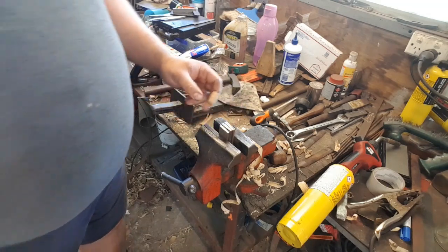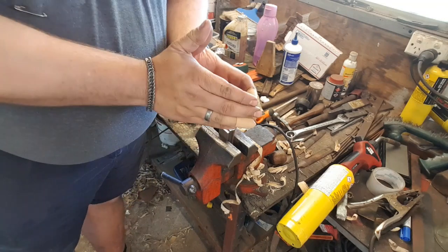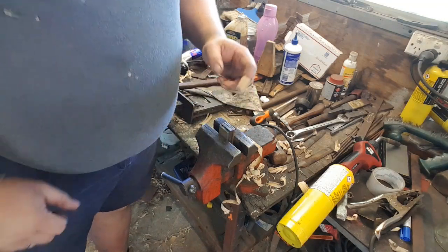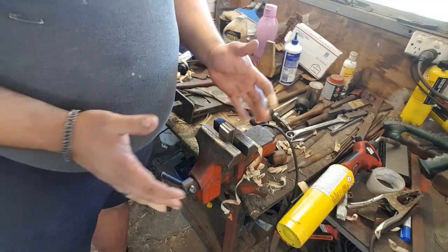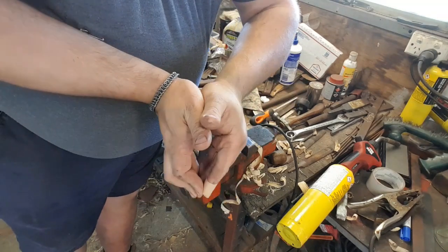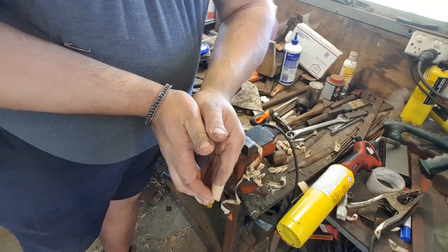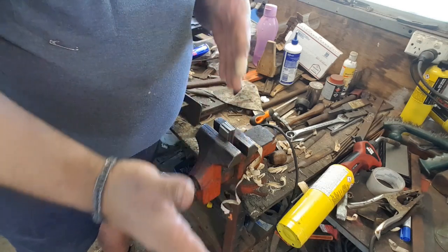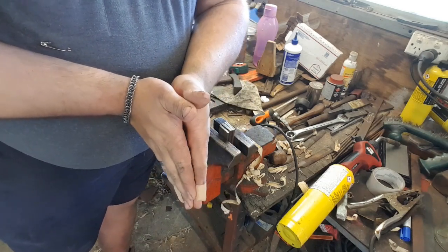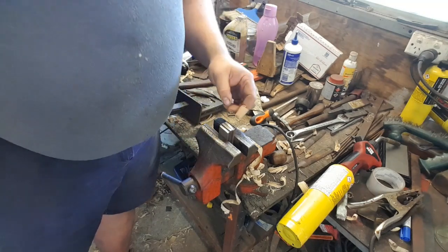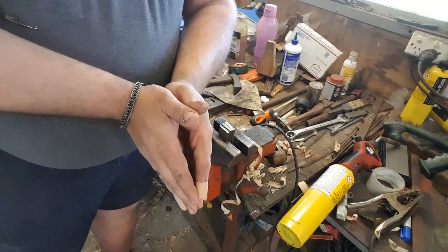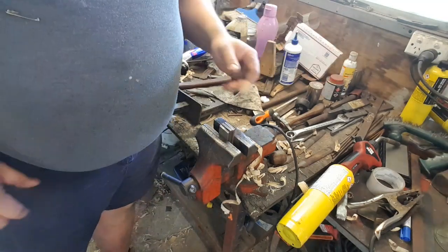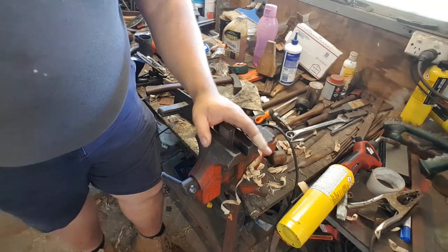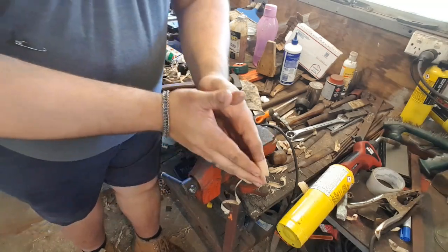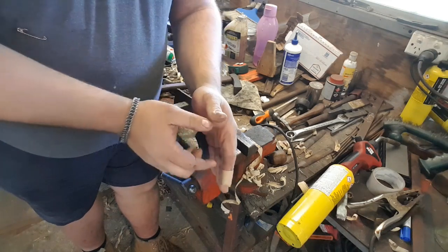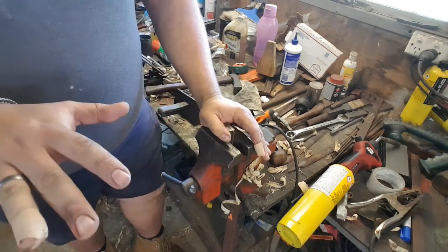One thing I didn't mention in the earlier intro was that you want to keep the thick material on the outside of your billet. The thinner the material, the more likely it is to bow in the heat, because obviously metal expands when it's heated up. And what happens is that the metal wants to force itself away from the heat. It's trying to force itself longer, but it can't do that if it's trapped at each end. So it's going to try and expand on you. The thicker material will resist that expansion, whereas the thinner material will literally bow out. And given that we're going to do one of these billets in the charcoal forge, if that bowing occurs, we're going to end up with charcoal in between our welding surfaces, and that's going to completely inhibit the weld.